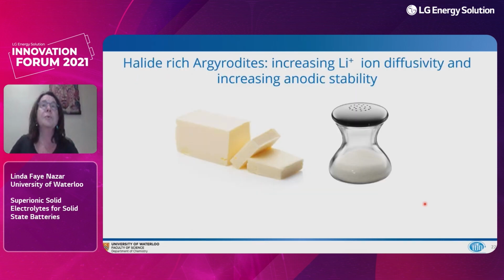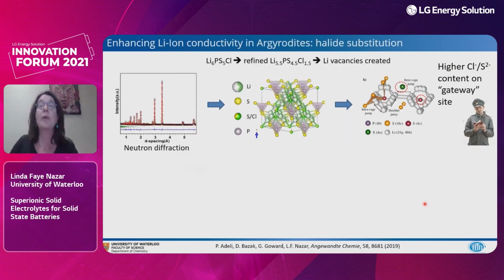So now I'll just switch to increasing the diffusivity by weakening the framework interaction. So I already told you about this gateway site. And so I mentioned that if we could increase the halide content, in other words, make the material halide rich, we would then populate this site with more halide, and we would now have not a really hardline customs official governing this interchange jump, but one that was a little bit easier in terms of a weaker interaction of a monovalent versus a divalent anion that sits on this site.